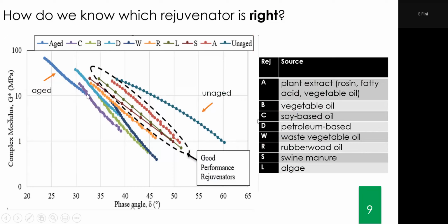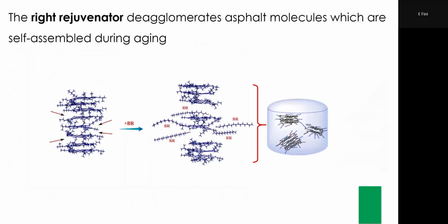So if you look at the slope of the blue, this violet, this blue, this green, they did not change the slope. That means the complex modulus versus phase angle did not change much. Yes, we did soften it, so complex modulus started coming down, but phase angle did not move forward as much. Ideally, we want this slope to become something like this, matching this curve, unaged. That may be impossible, but some of these actually change the slope and change the modulus together, which shows they are different.